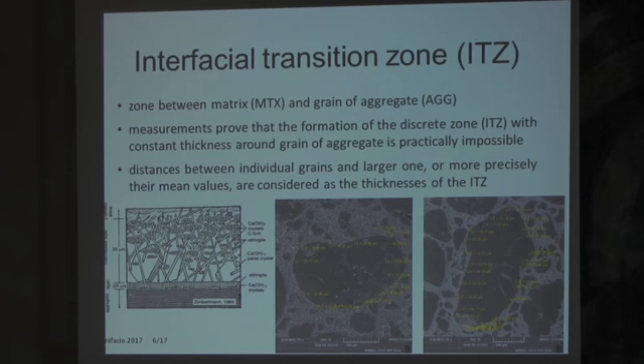So we decided to take into our modeling the thickness of the ITZ as the distance between the big grain and the other smaller grains, and we measured it in several points around the grain and took into account the mean value of this measurement. That means for the first composite we consider an ITZ thickness of 55 micrometers, and for the other one 40 micrometers.